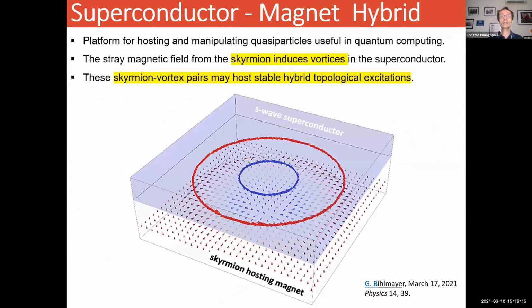So the major challenge is really to have a superconductor-magnet hybrid, and therefore develop a platform in order to host and manipulate quasi-particles which can be useful in quantum computing. And here the stray magnetic field, for instance, from the skyrmion, would induce vortices in the superconductor. And these skyrmion-vortex pairs may be the ones to host stable hybrid topological excitations.